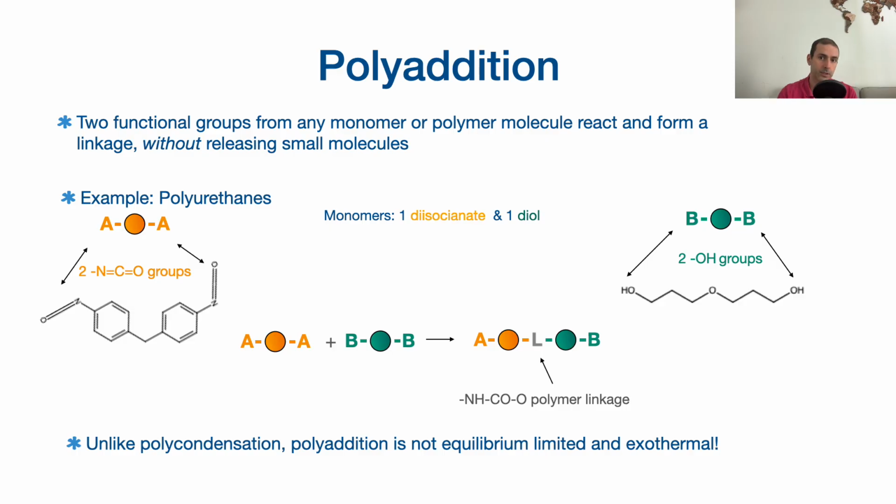Unlike polycondensation, polyaddition is not equilibrium limited and very exothermal. So here heat removal is really crucial as opposed to polycondensations, where heat and/or vacuum is needed to remove the small molecules released and to drive the reaction, which is typically endothermic. Okay? So now let us switch gears.